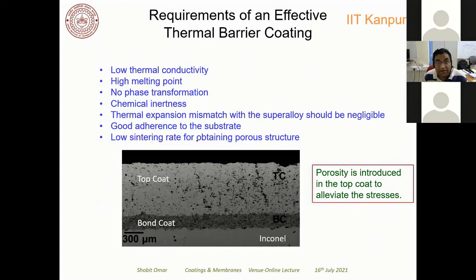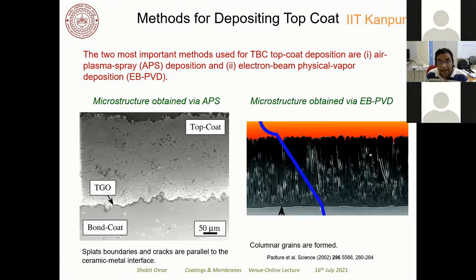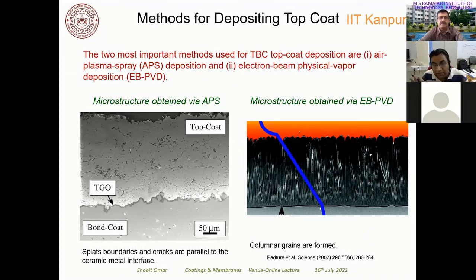So these are a few requirements of a thermal barrier coating, and you can see: low thermal conductivity, high melting point, no phase transition should occur, chemical inertness should be there, thermal expansion mismatch should be negligible, it should adhere very well to the substrate, and a low sintering rate for obtaining a porous structure. So to summarize, this is the last slide. Here I have shown you the microstructure of two top coats that are prepared from the air plasma spraying technique and from the electron beam physical vapor deposition technique.